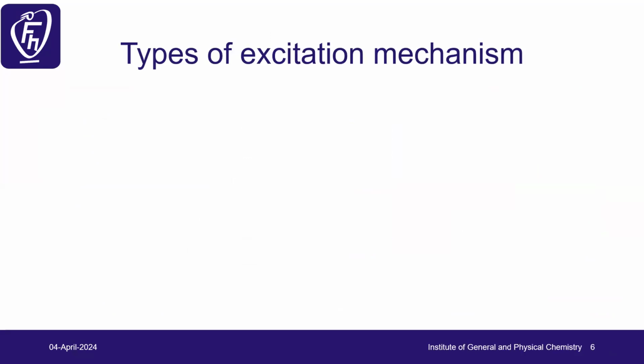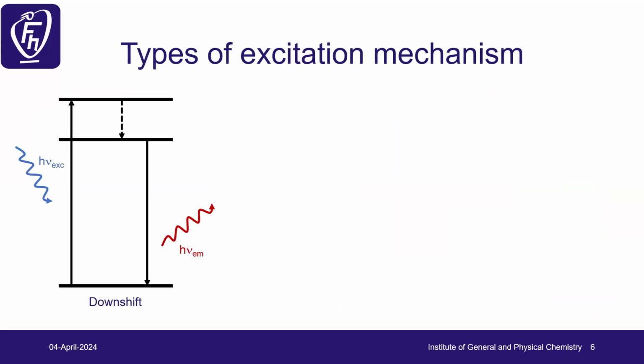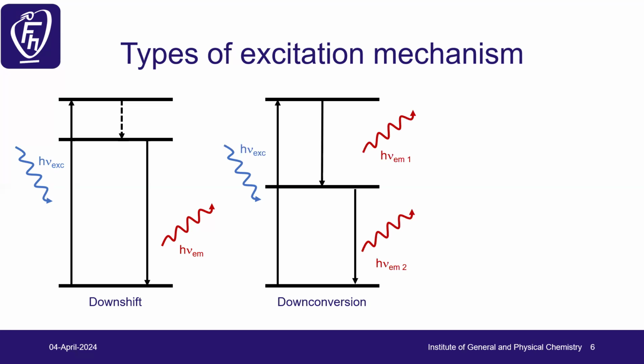So how can we excite them? We have three different mechanisms. Downshifting: we use high-energy photons like UV light, and then we have emission at lower energy. Or down-conversion, a two-photon process, where from one high-energy photon we get two lower-energy photons. This can happen in the infrared, so you can use a system with ytterbium and praseodymium, where praseodymium can be excited and then transfer energy to ytterbium, and then two